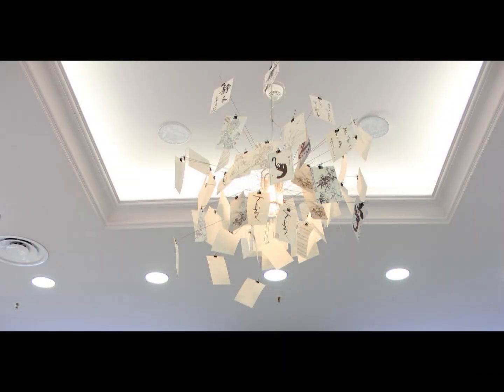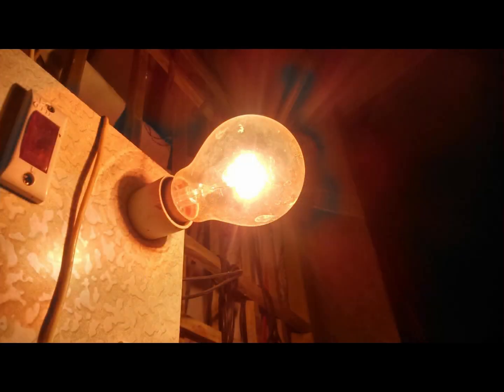Bulb blackening. In a conventional lamp, the evaporated tungsten eventually condenses on the inner surface of the glass envelope, darkening it. For bulbs that contain a vacuum, the darkening is uniform across the entire surface of the envelope. When a filling of inert gas is used, the evaporated tungsten is carried in the thermal convection currents of the gas and is deposited preferentially on the uppermost part of the envelope, blackening just that portion of the envelope.